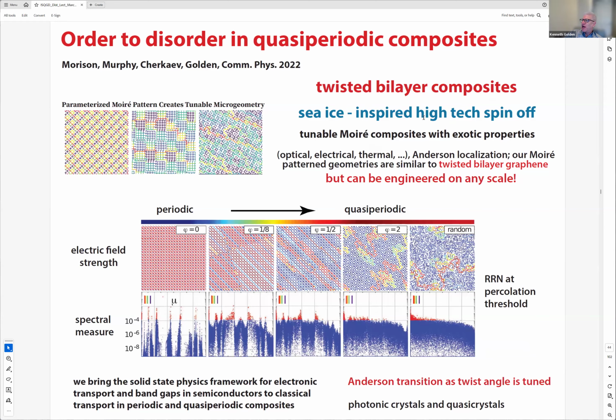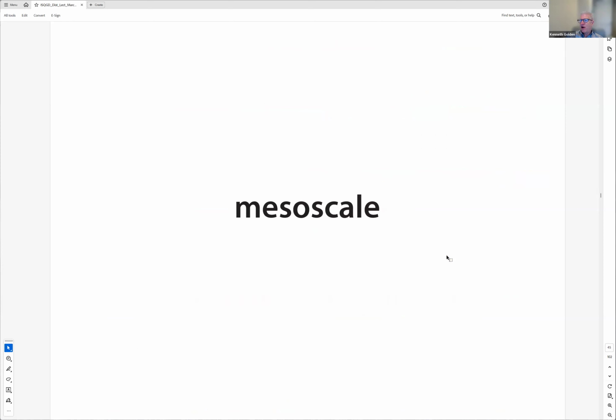And again, it's inspired from our sea ice studies. They're tunable moire composites with exotic properties. This is just a very small sample; there's an entire zoo of materials that you can generate depending on the twist angle. Here, note twist angle 0, and this is just a 2-degree change in the twist angle. We go from bands and gaps in the spectral measure to what looks like purely random behavior, where the spectral measure for this quasi-periodic deterministic medium looks almost identical to the spectral measure at percolation for the random resistor network. Anyway, there's a lot to discover here still. In other words, I think we opened this door and you can see all this amazing stuff, but we have yet to thoroughly investigate this whole class of moire metamaterials that we've opened up.